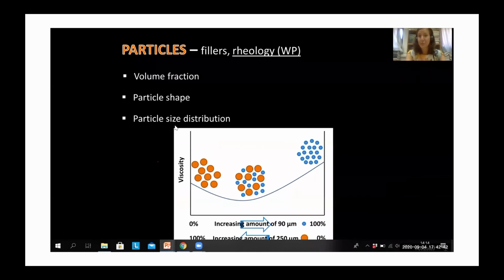And also the particle size distribution. So in terms of particle size and how the different aggregates are distributed in terms of granulometry will have an influence on rheology. So if we have, for example, two types of particles with a different size, so to simplify, I've put some big orange particles and blue small particles, we can see, for instance, that in terms of viscosity, so how thick, let's say, the grout is and how easily it flows, if we have a mixture of particle size, the resulting suspension is less viscous.